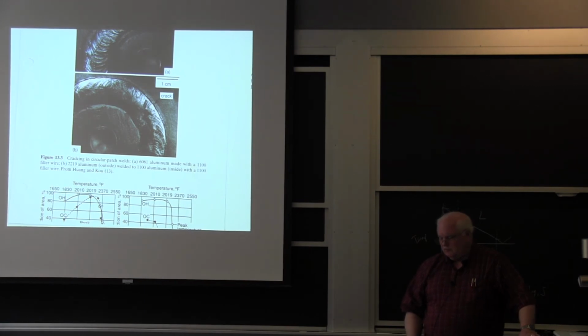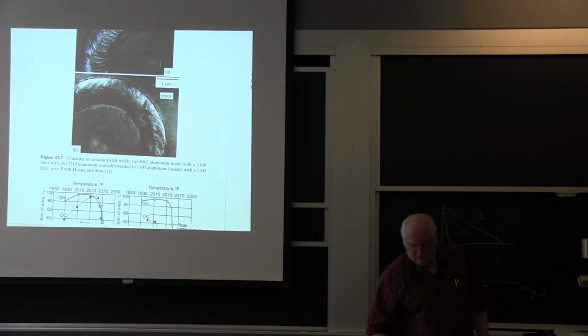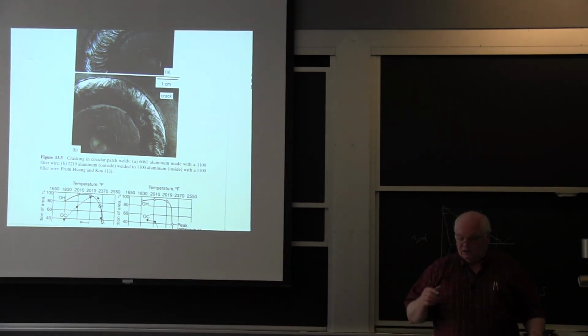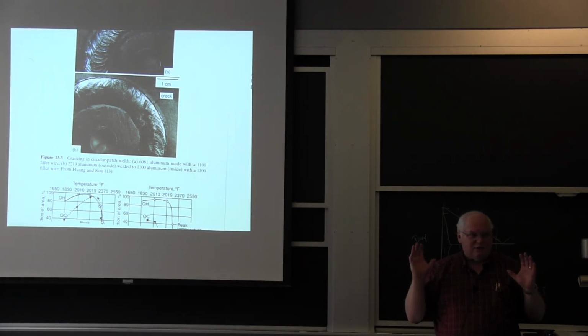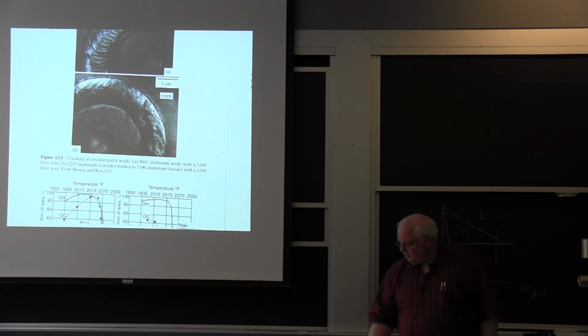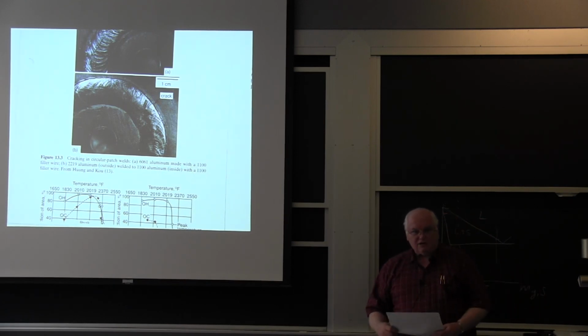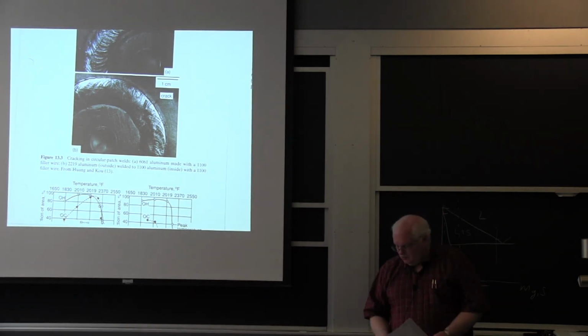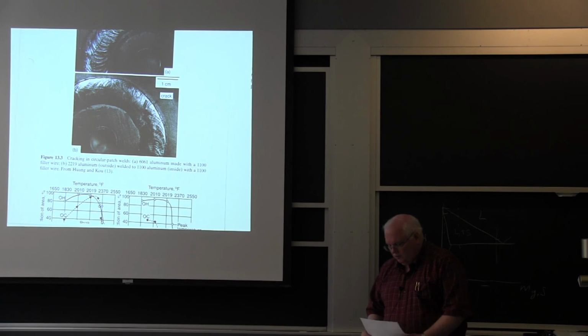In fact, when I was teaching an undergraduate lab a few years ago and I had to come up with some labs, I had the students weld 2024 aluminum, and it's perfect. You always get cracks. I mean, it's very easy to get cracks. In fact, I'll show you some of the data on that. And then they could take those cracks and put them in the scanning electron microscope and see dendrites, and it was great. Just not a great thing to weld.